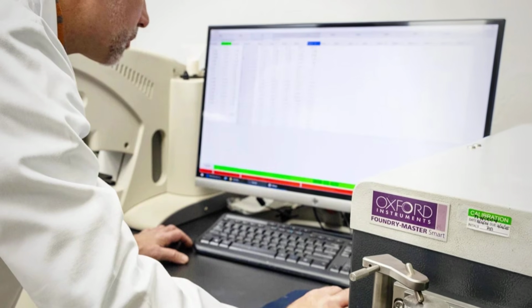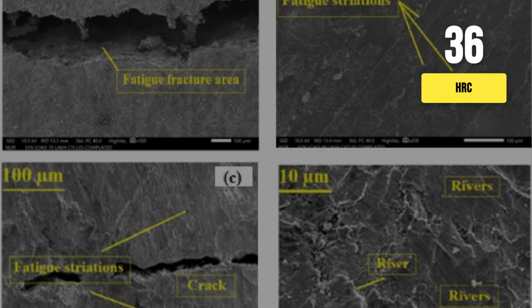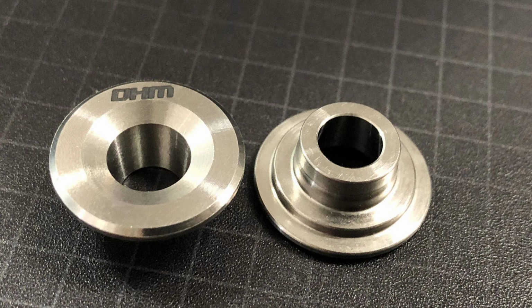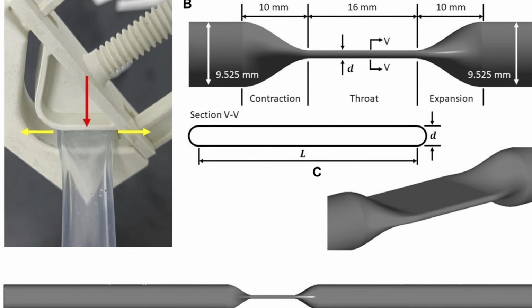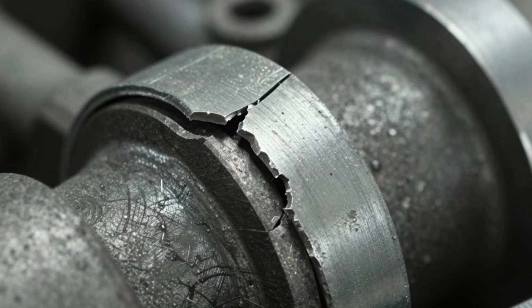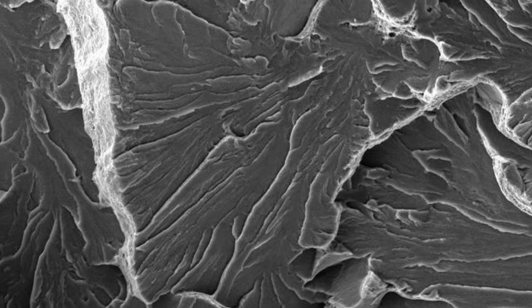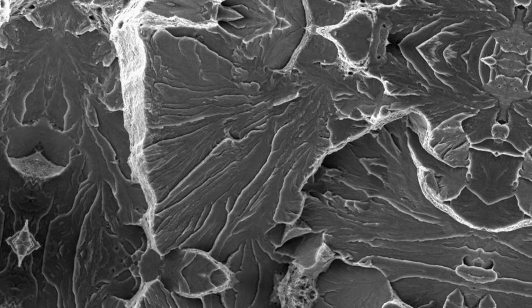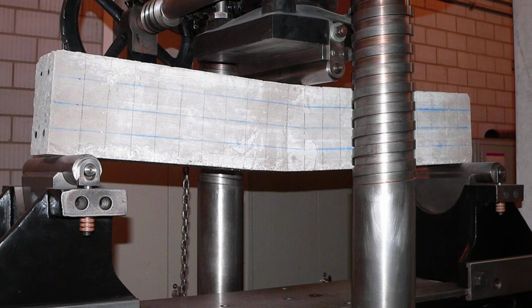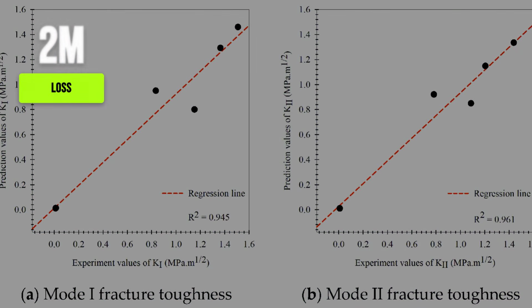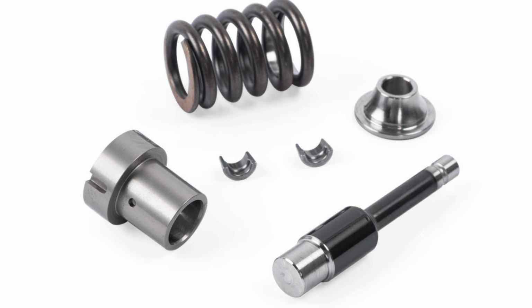The lab report is damning. Hardness mapping shows the retainer lip at 36 HRC, 12 points below the OEM minimum. The case depth measures just 0.19 millimeters, a quarter of the required thickness. The fracture photo from the lab is final. Brittle cleavage across the retainer lip, no evidence of ductile yield. KIC, measured by a 3-point bend test, falls to 65 megapascals times the square root of meter, a value that guarantees catastrophic failure under cyclic load.